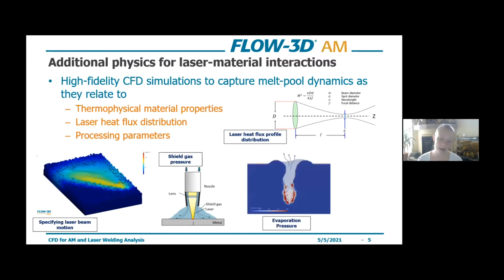And then evaporation pressure is extremely important, also referred to as recoil pressure. So this is yet another additional pressure force on the surface of the material, and it's due to the rapid vaporization of the material as it's melting, and it can lead to keyholing, it can lead to morphology in the melt pool. So that's an important phenomenon that we account for.